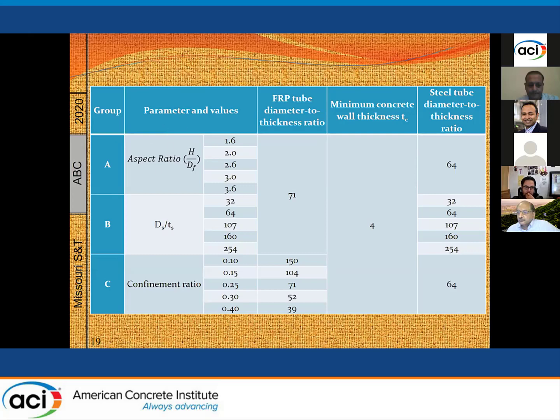For example, in group number 1, group A, we consider the aspect ratio, so the height of the column divided by the diameter, and diameter Df, this is the outer diameter of the FRP. We look at different aspect ratios ranging from 1.6 to 3.6. And then we look at the FRP tube diameter to thickness ratio. For groups A and B, we kept this at 71. So this is the diameter over the thickness of the FRP. And for the concrete thickness, for groups A, B, and C, we kept this at 4 inches,